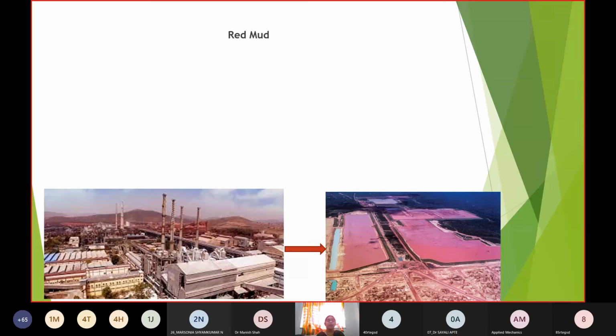So for every 1 ton of alumina that is being produced out of bauxite by Bayer's process, around 1.5 to 2 tons of red mud is being produced. So around 1.5 to 2 tons of red mud is being created when alumina is being manufactured. I cannot cut down on utilization or production of alumina for the growth of the economy, for the demand that I have to meet. Hence, I continue the production of aluminium, I continue the production of steel, power, everything. But I cannot cut down on these byproducts that are coming out.